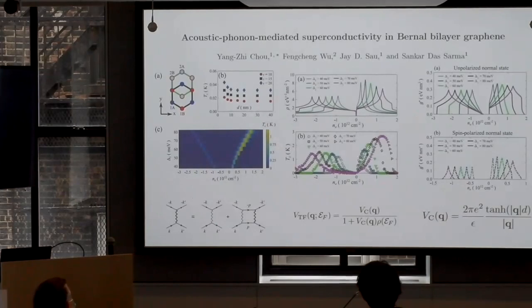Okay, but that's not where the story ends. Then Andrea calls me 6 months after that. Now he seems to have seen a superconductor in Bernal bilayer graphene, which is the standard bilayer, not twisted. Twisted bilayer graphene is a variant on this, but this is not twisted. Here, the most important take-home message is that TC is very low. Look at TC, it's on the order of 20 millikelvin. Before it was like 1 to 2 Kelvin.